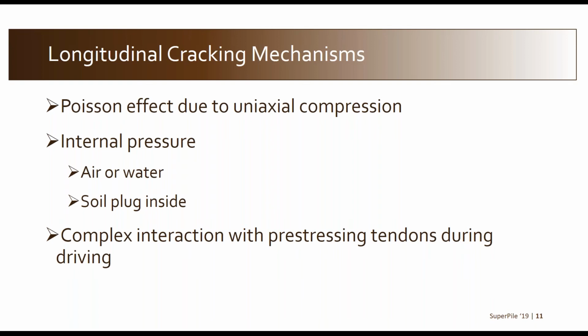Internal pressure: because this is a hollow cylinder and we're driving it, there's a combination of air and or water in most applications inside. So there's a dynamic compression of that fluid inside, which then puts a pressure on the wall and wants to push out, which could potentially be enough to cause rupture or splitting. That's combined with the fact that a soil plug may or may not be forming. So this thing is sort of getting compressed from the top and or the bottom simultaneously as it moves down. So there's a degree of complexity there, certainly, with that aspect of the behavior, the hydrodynamic pressure inside.